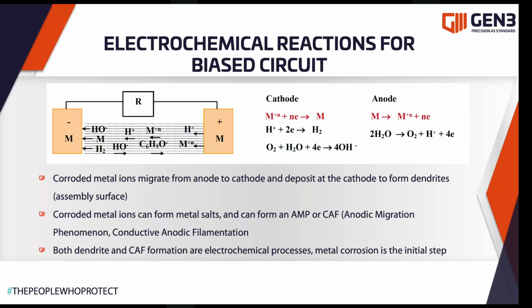But we can also have the opposite occurring when there's a very limited amount of moisture around and solubility is an issue. So in terms of anodic migration phenomenon or conductive anodic filamentation, subboard phenomena where moisture is limited, we get conductive salts being formed. So they by contrast grow from the anode towards the cathode, and they are very much dependent on the moisture being left in the board for conductivity.